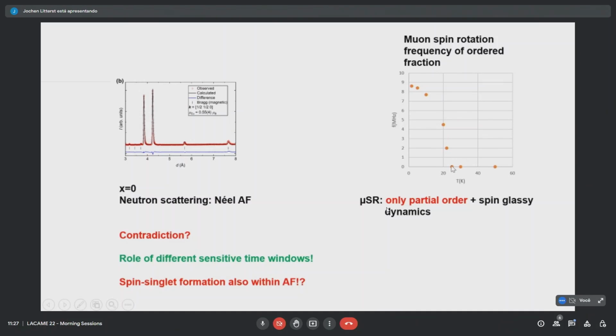Now the ordered part follows a nice magnetization curve in frequency that corresponds to the local field, which is quite normal. But why is there this superposition? Is there a contradiction? Well, we have to keep in mind that neutrons and muons see somewhat differently. The time-sensitive windows are different. Elastic neutron scattering is fast. Here we are relatively slow with the muons, in the range of microseconds to nanoseconds. Here we are below 10 to the minus 12 seconds with the neutrons. Therefore, it's no contradiction at all. Simply, the neutrons cannot see this slow dynamics in elastic neutron scattering. One should look for inelastic neutron scattering.